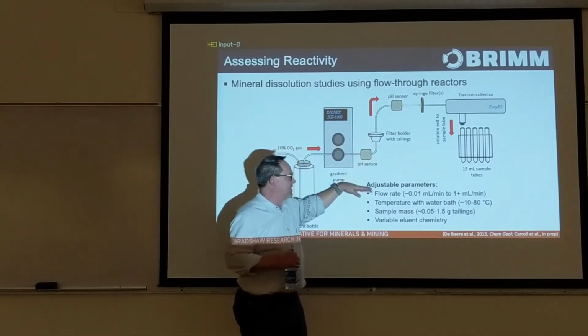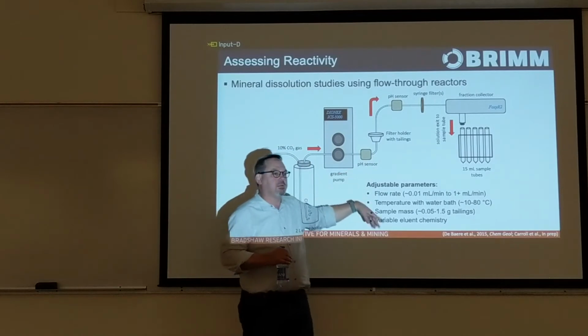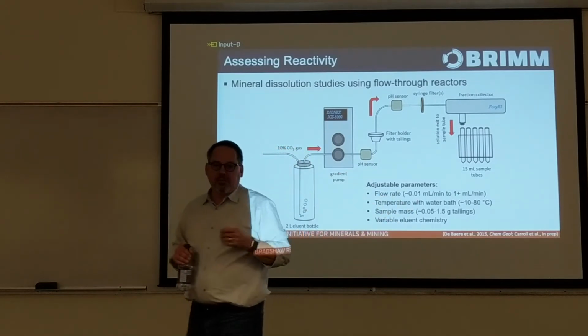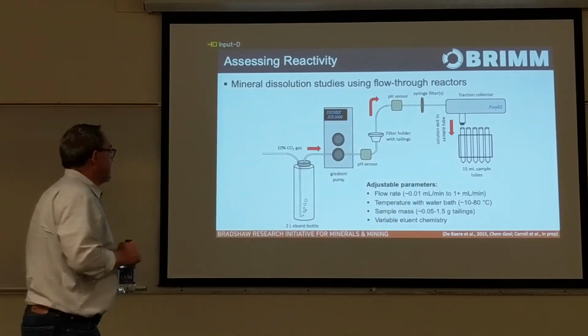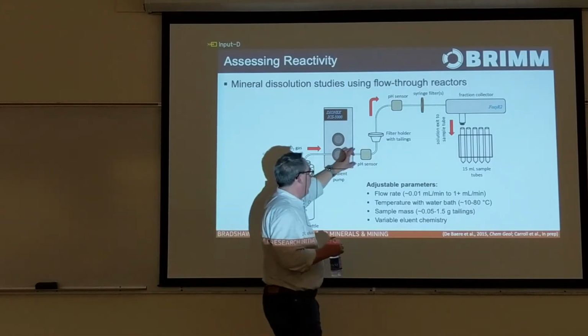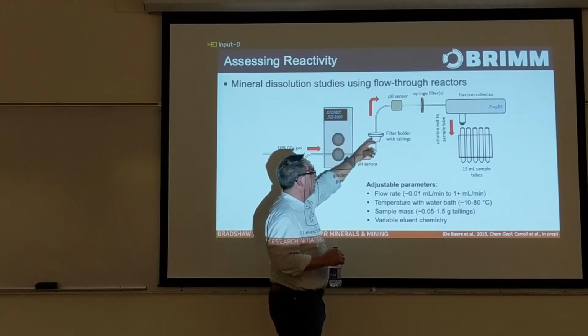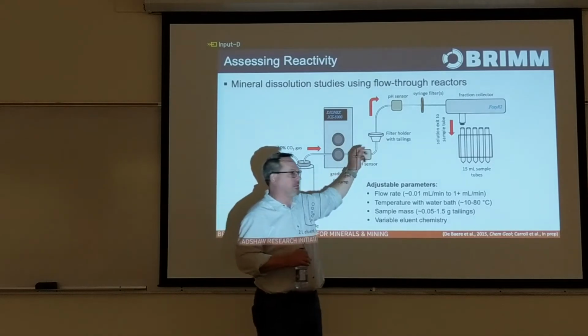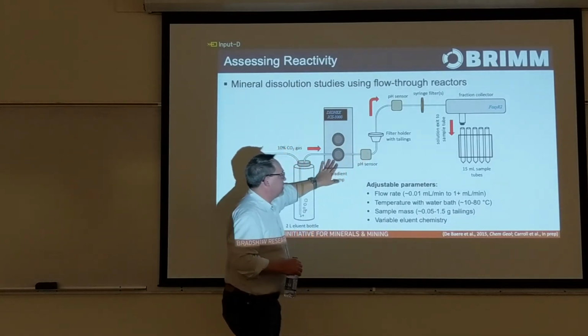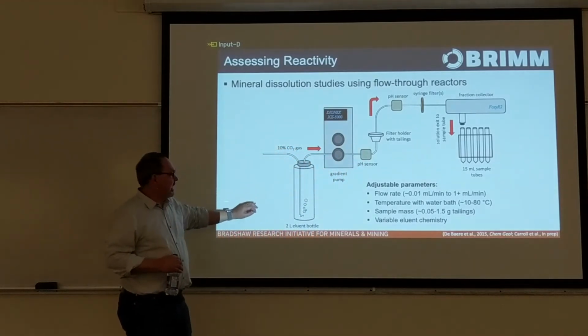We can measure them in this system. It's a highly tunable system, so we can vary the reactive parameters by about 2,000-fold by changing the flow rate, the thickness of the tubing, and the dial of the pump to change how much tailings are reacting. But the important thing here is we're measuring the reactivity of tailings.